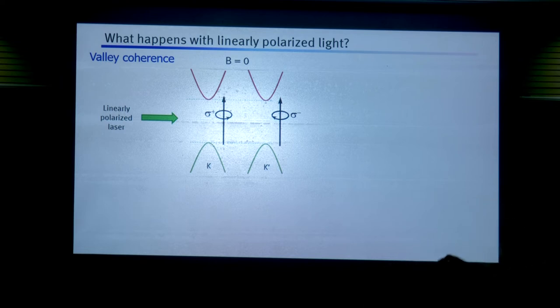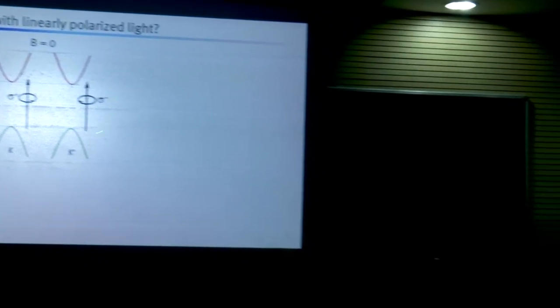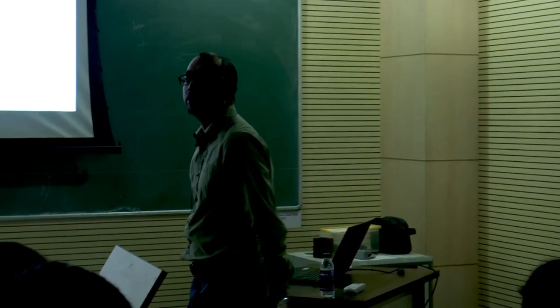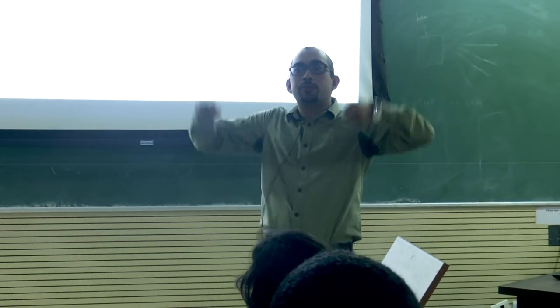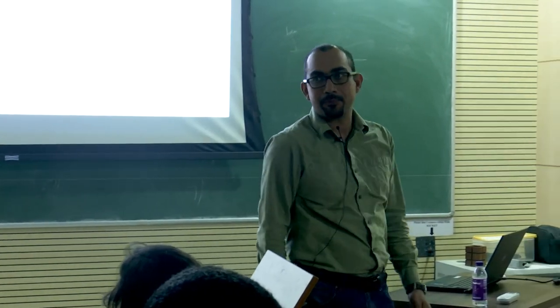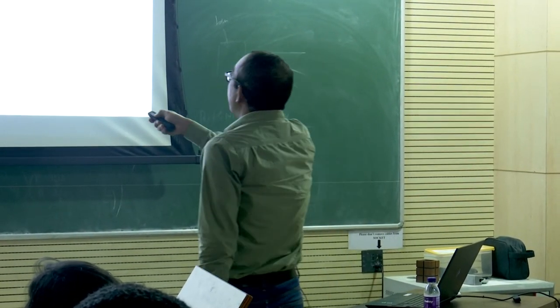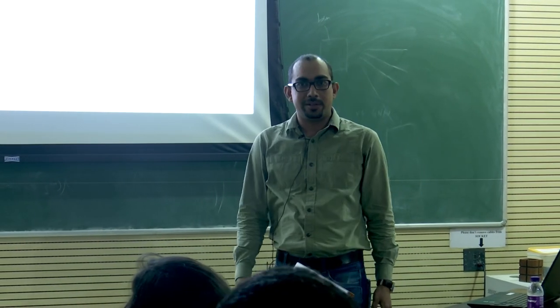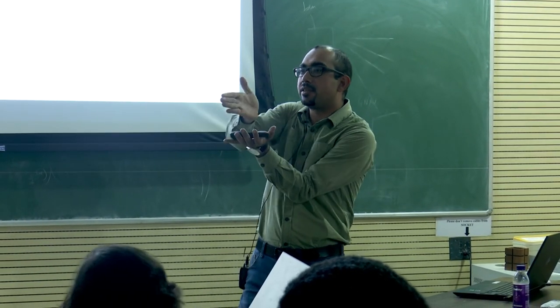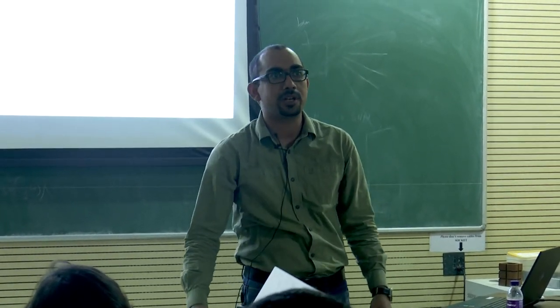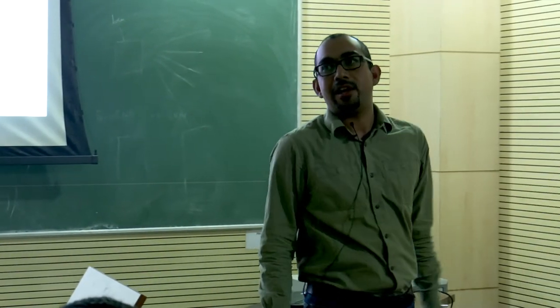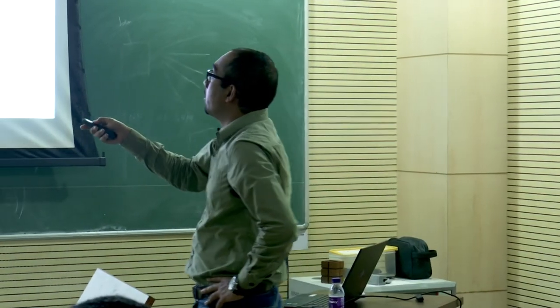Now, these two valleys, since they are coupled to the circularly polarized light, what if we shine linearly polarized light? Linear polarization is a superimposed state of two circular polarizations. It turns out that this linearly polarized light actually creates a quantum superimposed state of these two valleys. So it excites both valleys together as a single state. This is a quantum superimposed state. And what happens is the emission is also linearly polarized. So you change the polarization of the incident light, and the emission also keeps on changing polarization. This means that the valleys are coupled, and this phenomenon is called valley coherence.